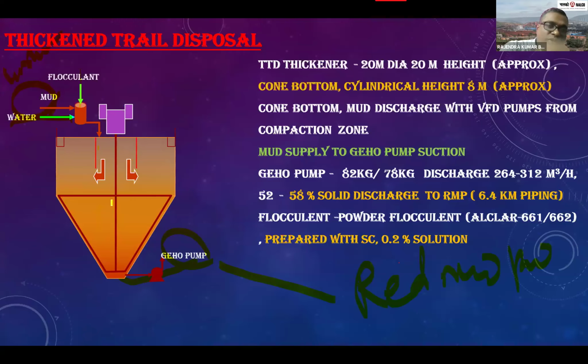settle it over here. And this is your TTD, thickened tailings disposal method. TTD thickener is 20 meter diameter and 20 meter height. Bottom cylindrical height is 8 meter approximately. Cone bottom mud discharge with VFD pumps from the compaction zone. This is the mud supply to the gear pump. Gear pump is 82 kg, 78 kg discharge, 264 to 312 meter cube per hour, 52 to 58% solid discharge, 6.4 kilometer piping, powder flocculant.